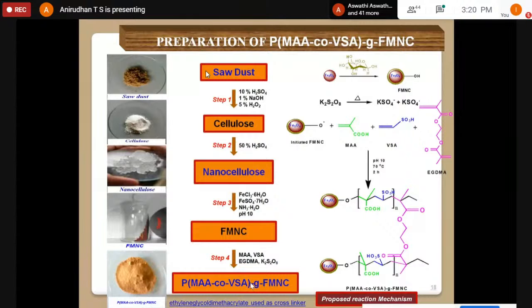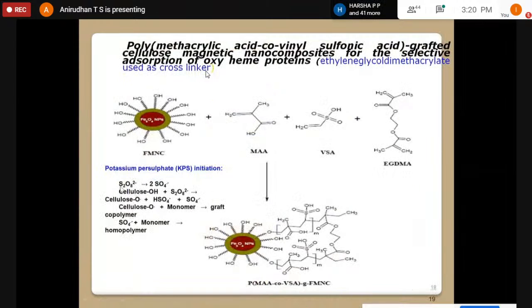So in that way you can utilize different types of monomers to graft on the surface of your iron oxide treated magnetic nanocellulose. So here I utilize free radical mechanism. Free radical mechanism is one of the most important methods for grafting copolymerization. So we utilize potassium persulfate as an initiator, and the most important property coming from this is, once you introduce an initiator, that initiator itself decomposes into fragments, and a sulfate group is formed, and this sulfate abstracts one hydrogen atom from this cellulose, because cellulose contains primary alcoholic OH group and secondary alcoholic OH group.